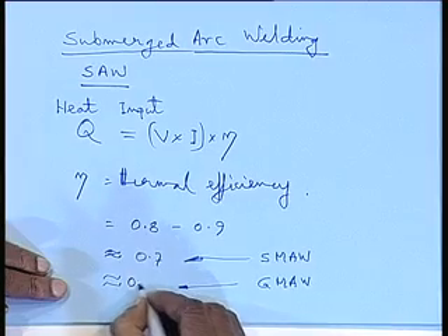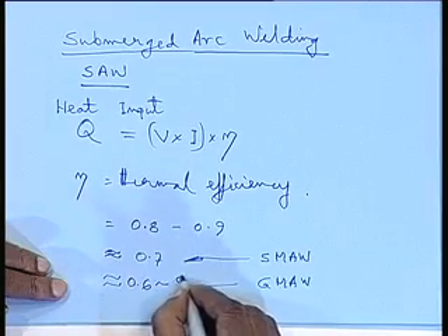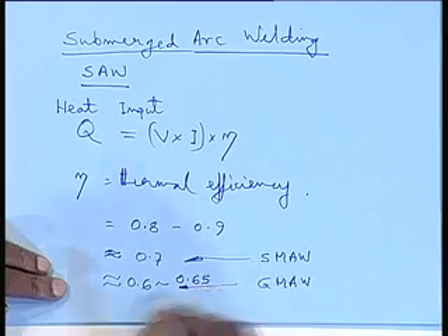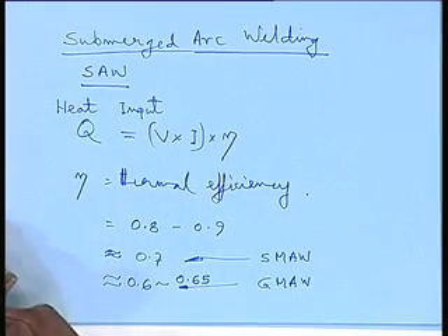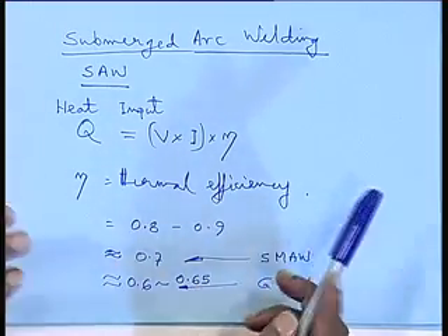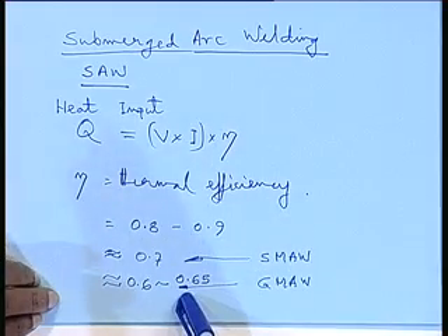So, gas by force is going and going away. So, it is by convection, it will take out a lot of heat. So, heat loss is more. It is not that low as 0.5, but it is of the order of 0.6 to 0.65. So, in gas metal arc welding, there is a lot of heat loss, because this is important.